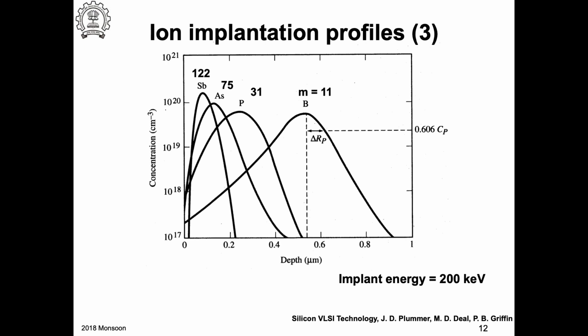So you can see what is happening here is that the lighter the element, the deeper it goes. This is a very important observation. And obviously these profiles are not Gaussian, none of them. It's not symmetric about this one, so you can see that immediately. So it actually spreads more into